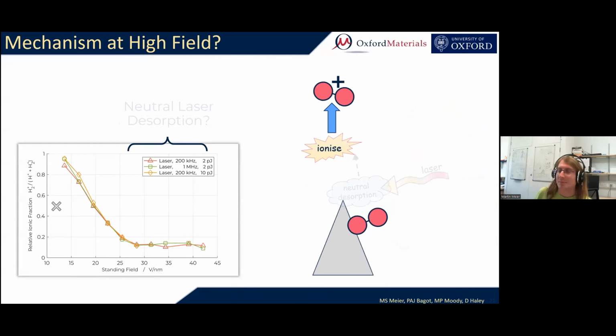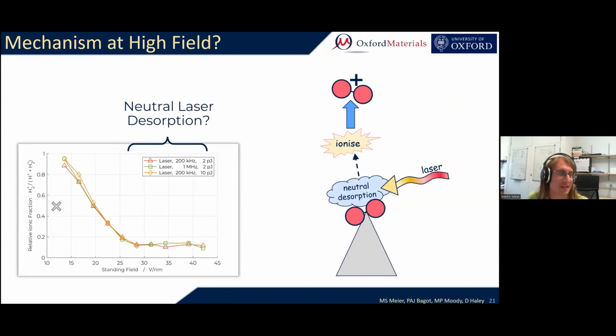There is a second possibility that has been discussed in the literature, and this is that the laser could cause neutral desorption of hydrogen-2 from our tip. This will then fly away, and eventually it will ionize at a critical distance and then fly into the detector. Once more, we have that advantage of the away-from-surface ionization, which could possibly explain an energy deficit. But there's also a problem with this theory.